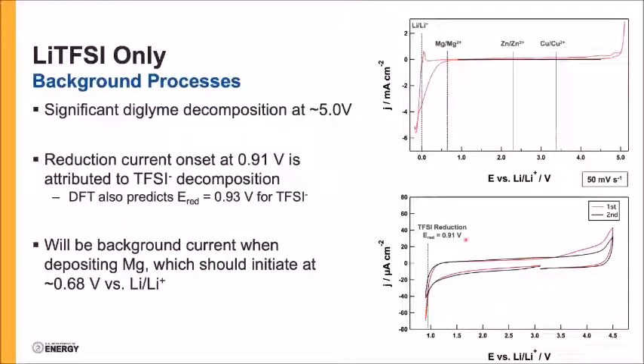But what this means is that there's definitely going to be some background current when we're depositing magnesium, which should initiate about 230 millivolts below this. That does complicate the analysis a little bit. You can see that a bit in what comes.